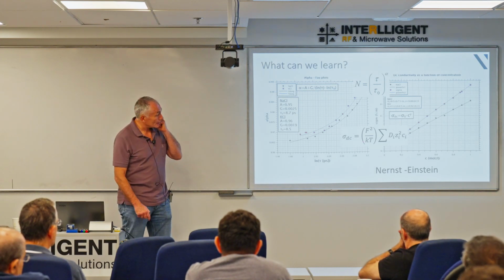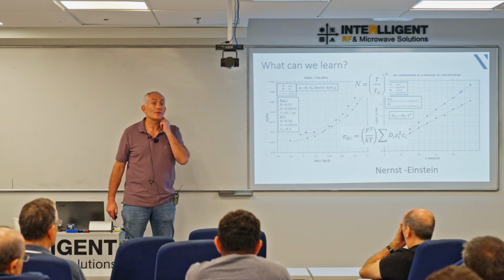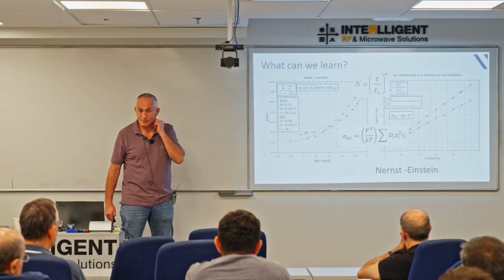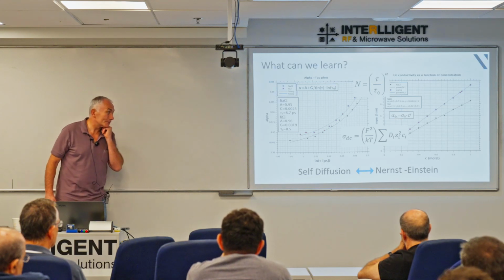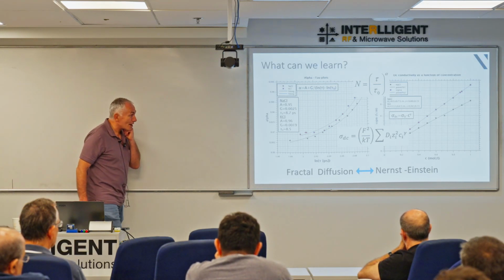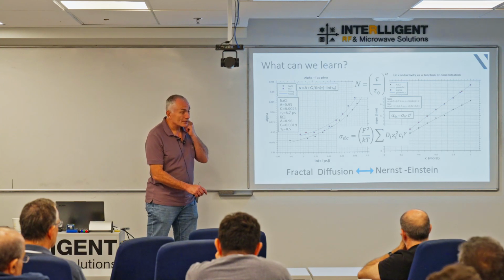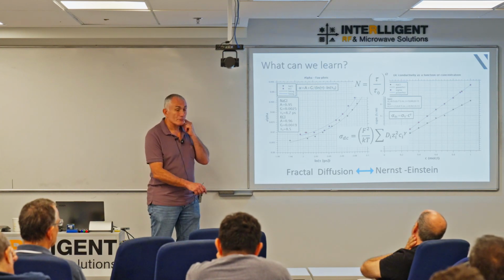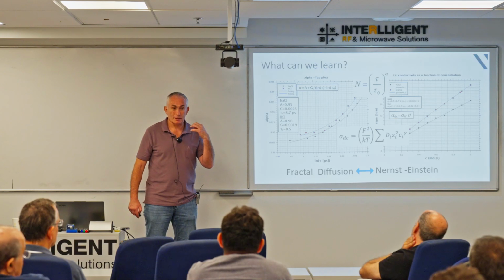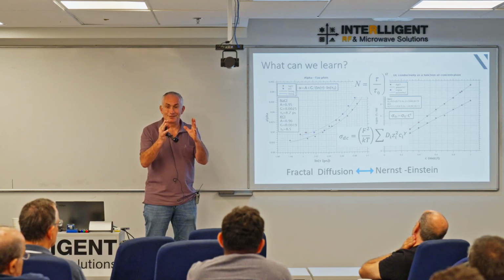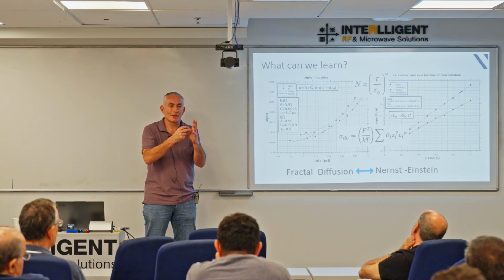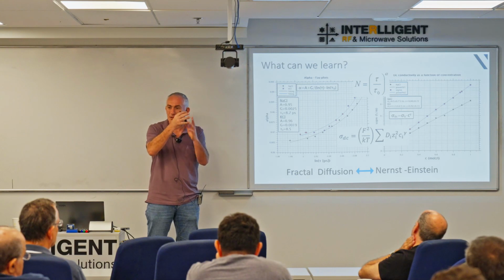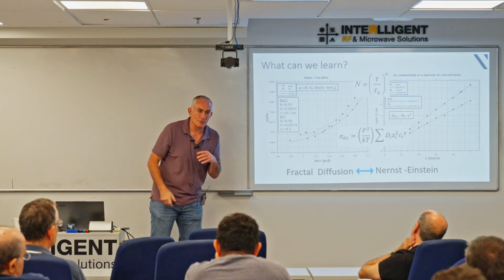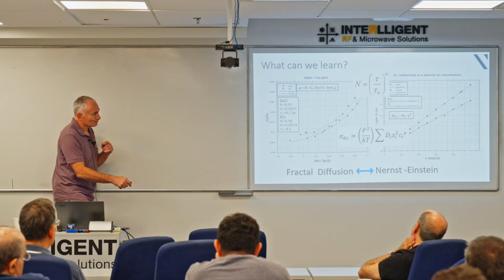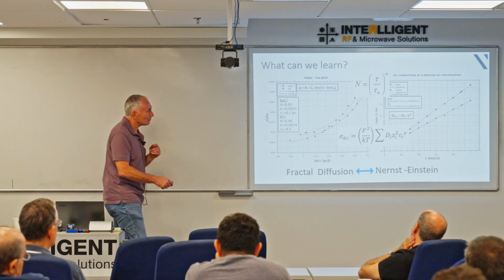It doesn't work here because this is not self-diffusion, as we already talked about. It's anomalous diffusion. And so you have to make it fractal. So you have to put in here an exponent. That exponent reflects, if you like, the motion of ions to come to the electric phase interface, because it's DC conductivity, and actually get through a double layer of ions accumulated at that face and come through the other side. So, more information. All this from one measurement.